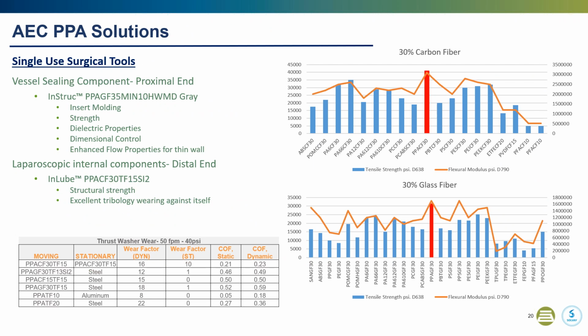And we have thrust washer wear, which is the chart to the left on the bottom. We have wear data on every polymer wearing against other polymers, and different formulations wearing against metal. This is to showcase PPA CF30 TF wearing against itself, and you see a wear factor of 16 and 10. Please note that this data is available for your use. Any wear number below 200 is excellent. We also show different formulations of PPA with glass and Teflon only, wearing against different types of metal, and we also have it in different temperatures, 70F, 300F.